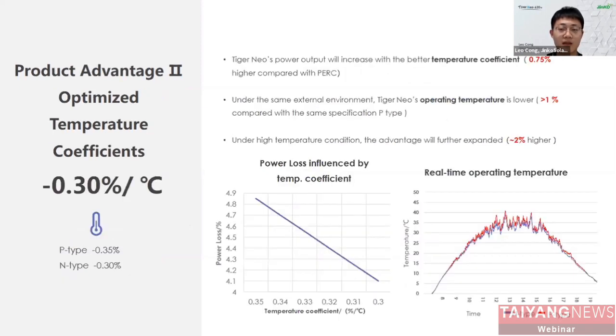illumination. And secondly, in terms of module temperature coefficient, Jinko 182 N-type modules can achieve an optimized temperature coefficient of -0.3% and increase the average power by about 0.75%. At the same time, the Tiger Neo series modules operate at an average temperature more than 1 degree centigrade lower than the P-type of the same specification. Combined, power generation can be increased by up to 2% in high temperature areas.